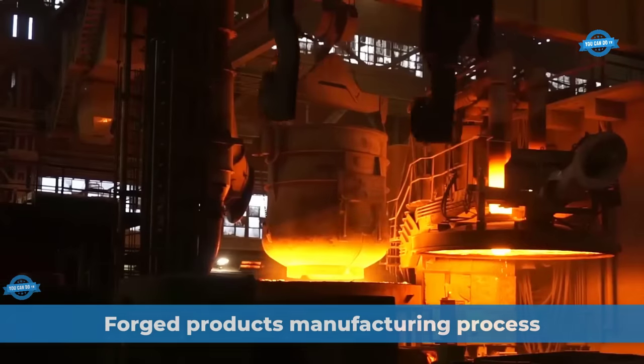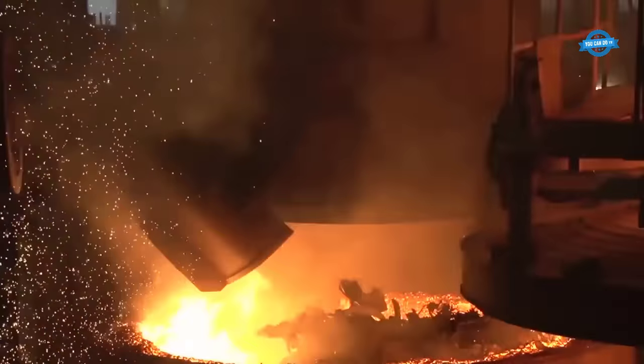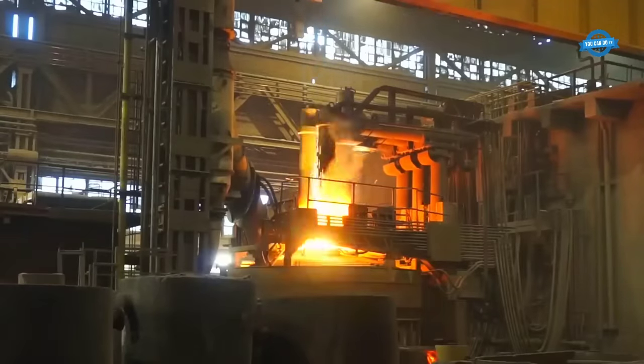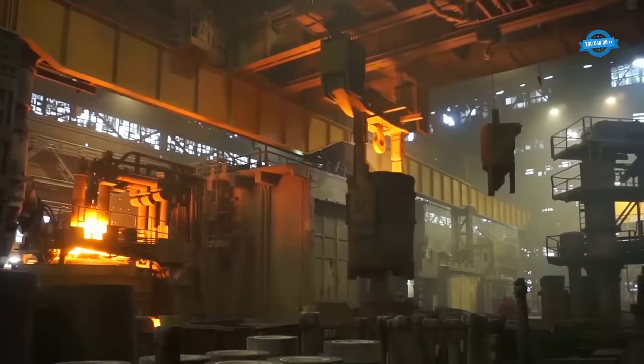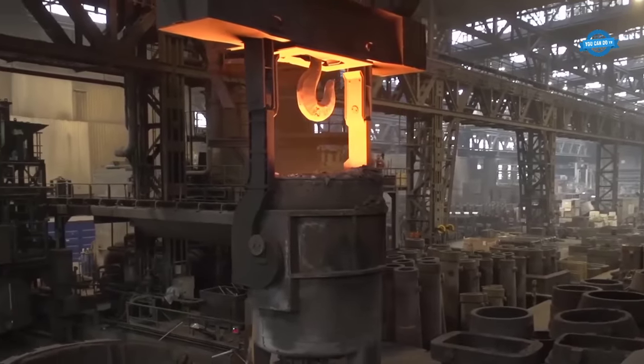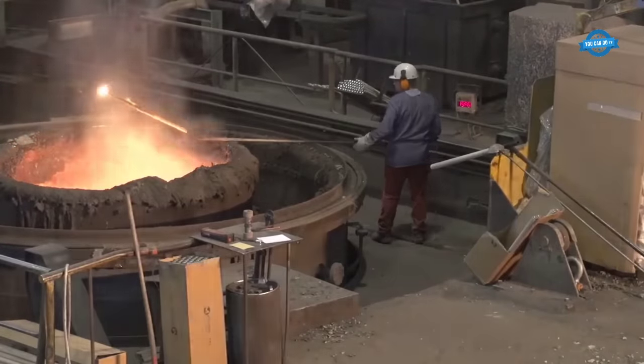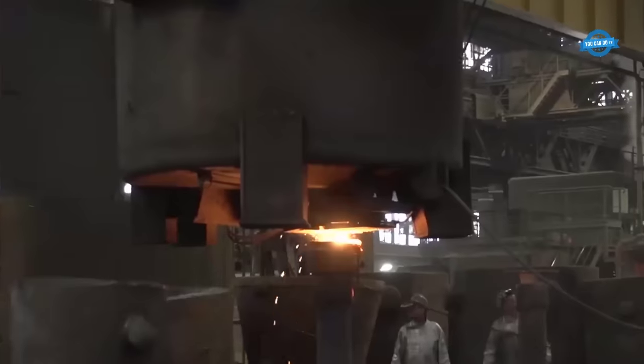Schmiedewerke Gröditz, the GMH Group factory, operates an electric arc furnace capable of producing a maximum of 50 tons of liquid steel per load. The furnace utilizes sorted scrap, meeting the necessary requirements for melting. Once the smelting process is complete, tapping is carried out. Following the smelting process, temperature and alloy adjustments are made during the subsequent ladle furnace treatment. In the VD, vacuum degassing, or VOD, vacuum oxygen decarburization unit, dissolved gases are released from the smelted mass.